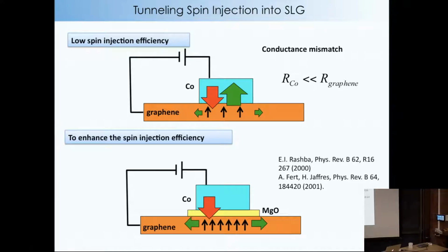And this is a known problem in semiconductor spintronics. So you have to somehow get around this problem. And it's known even theoretically and experimentally how to do it. But what you do is you put a tunnel barrier in, and then you inject with a bias to get the stuff in. But then, it's going to have a hard time backflowing because this tunnel barrier, like MgO tunnel barrier, will prevent a lot of this backflow, and it will allow the spins to stay inside the graphene. So this is the conductivity mismatch problem, and this is a solution to get around it.